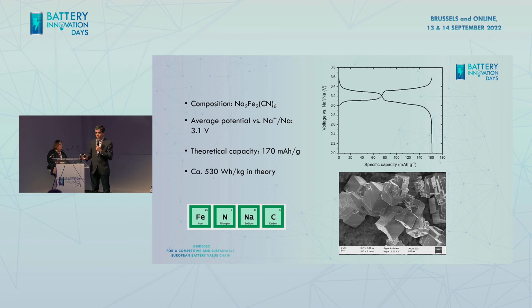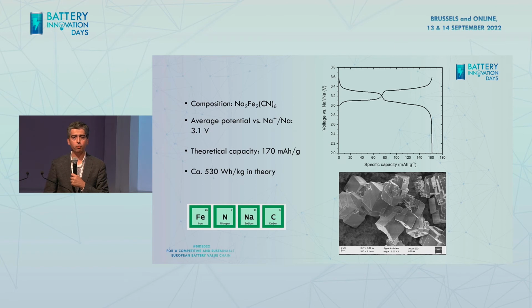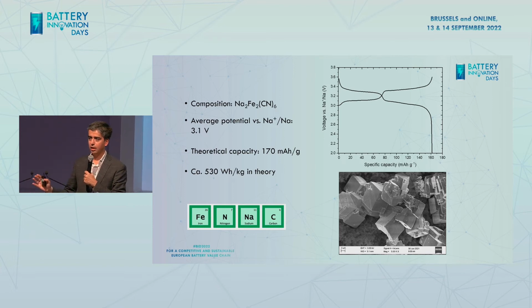So this is not a new material. This is part of Prussian blue analogs, which has been around for many, many years. It has been used in painting and so on. But it's very interesting because if you manage to remove all the water out and have 2 sodium in the material, then you're going to get actually a very high capacity of 170 milliamp hour per gram. This is roughly in the range of LFP. And the potential is almost 3.1, again, in the range of LFP. This becomes very competitive to lithium-ion batteries then.